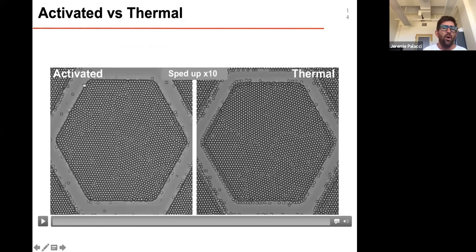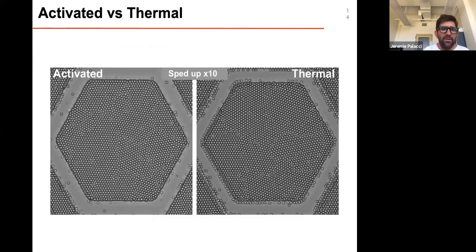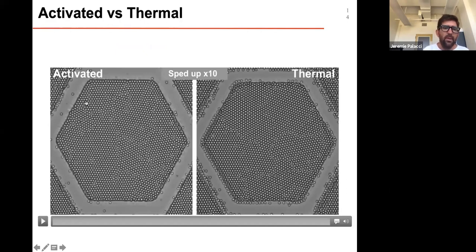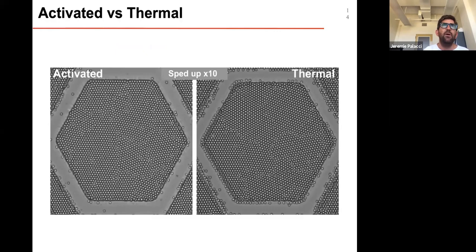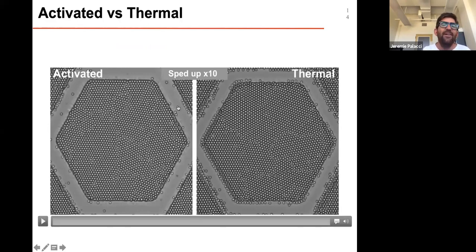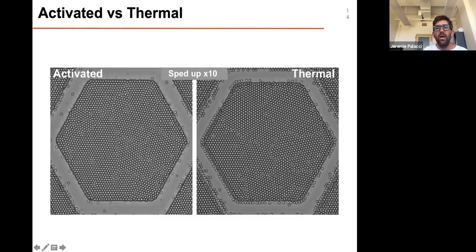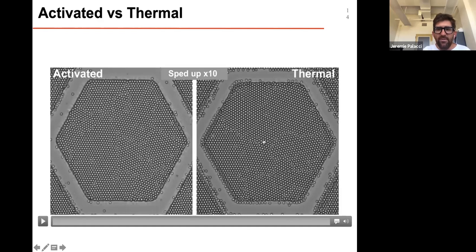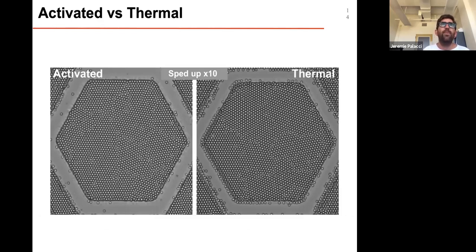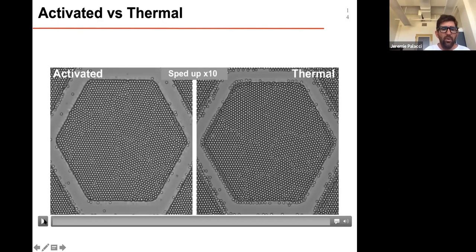We take those 5 micron spheres and let them sediment in microfluidic arenas, which are hexagonal and assist the crystallization. On the left side, we have those particles in an arena, with 5,000 passive spheres and roughly 1% active spheres. We change the surface fraction, but we typically have something like 20 to 60 active particles in 5,000 passive. The right side is an equivalent experiment, with 5,000 passive spheres and the same active particles, with one difference: we won't turn on the light. So the active particles will never be activated. They will just remain passive. This system is completely passive and thermal, while the other system will be active. Now I will show you what happens when we turn on the light.